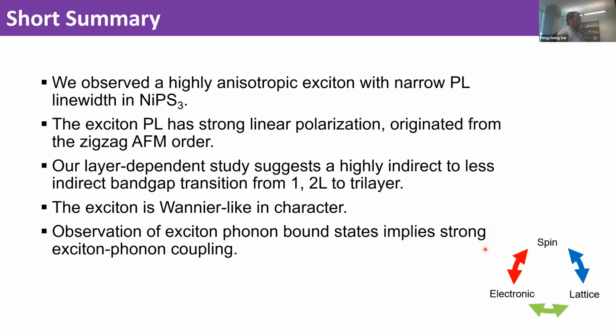Questions? Actually, I have a question myself. So when you thin it down, do you actually know what happened to the magnetic structure of the system, or the Curie temperature, or Néel temperature? Yeah, the Néel temperature, when you go very thin, like trilayer or bilayer, it drops a little bit, like a few kelvins. So by monolayer, do you still have antiferromagnetism, or not? Monolayer, I cannot make any conclusions. It may actually be non-magnetic, maybe yes, maybe not, because the signal to noise ratio is not very convincing. But the bilayer is very convincing, we have it. Monolayer, from my point of view, if you ask me, I will say yes, we have magnetic order, but the data quality is not good enough to be conclusive.